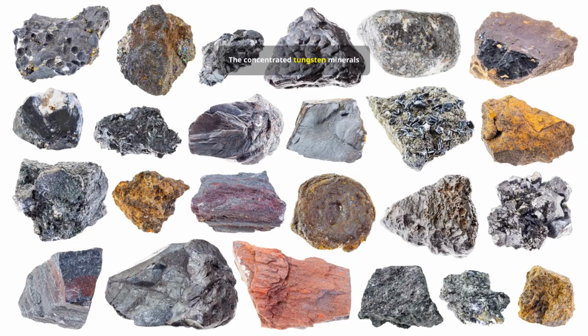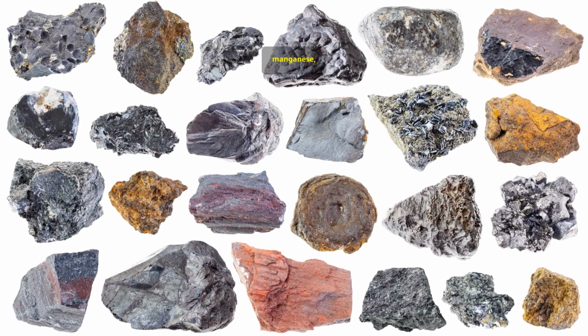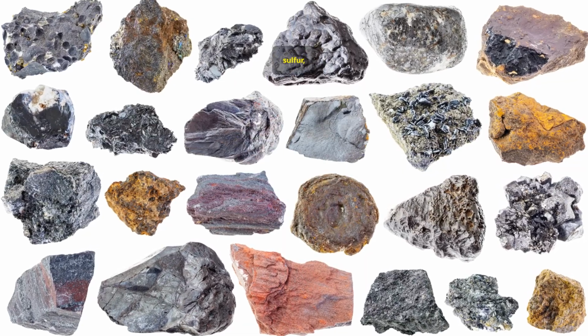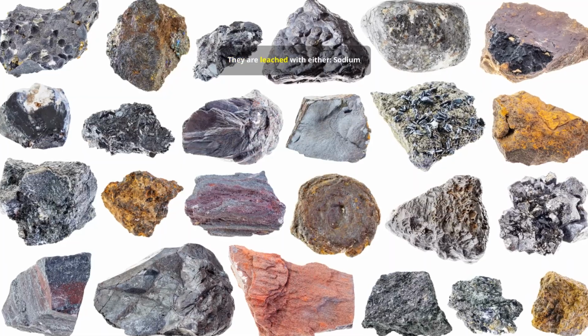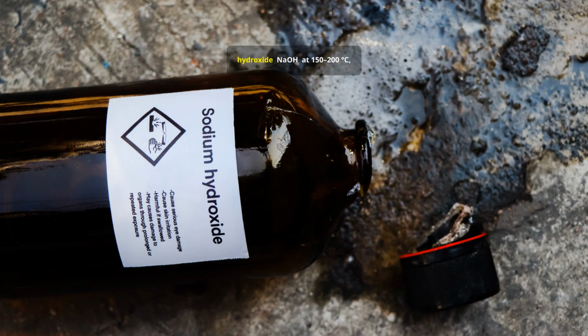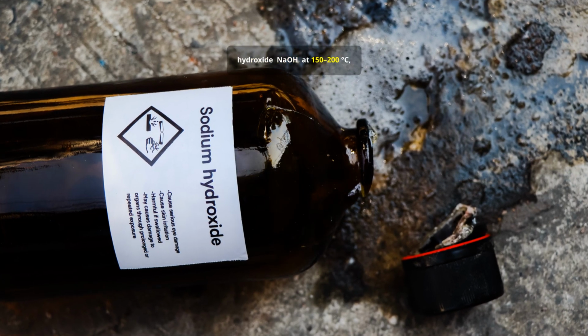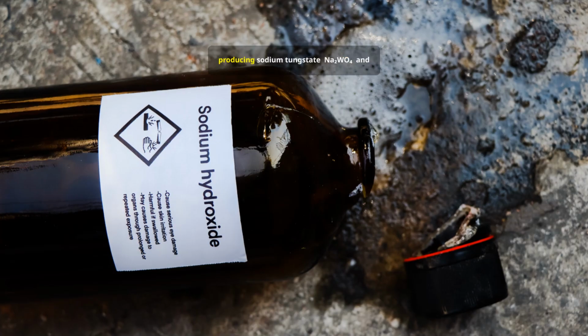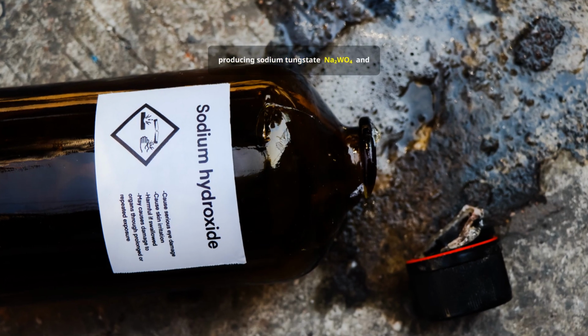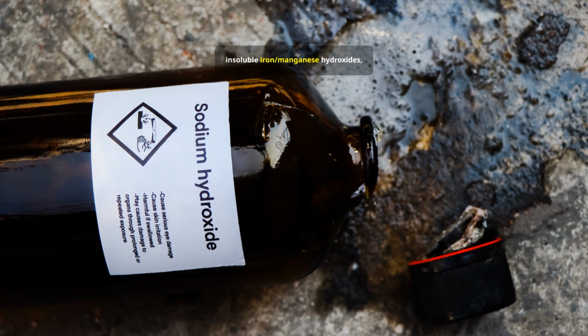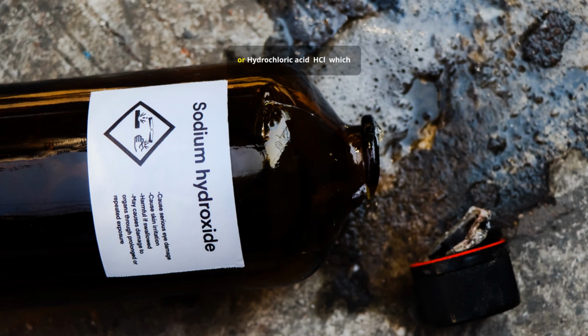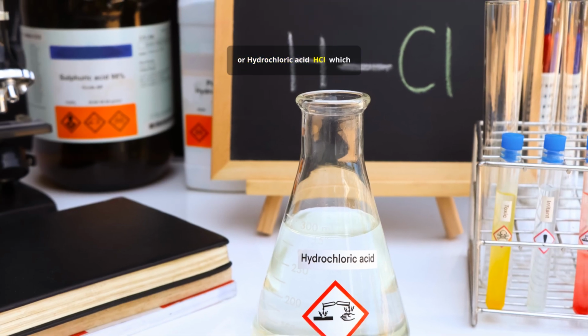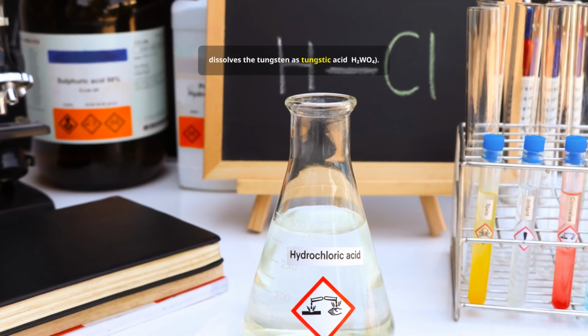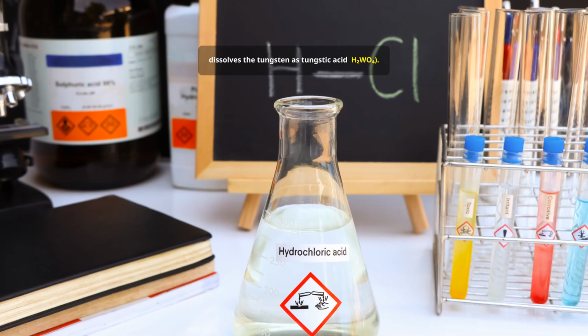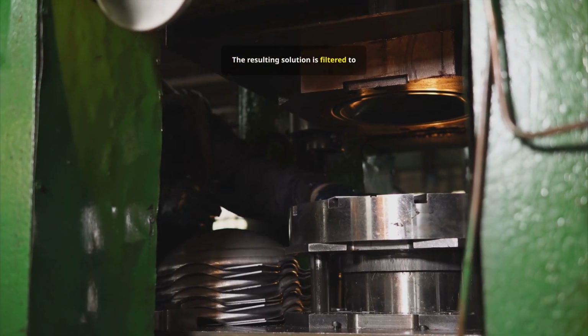The concentrated tungsten minerals still contain iron, manganese, calcium, sulfur, and oxygen. They are leached with either sodium hydroxide, NaOH, at 150-200 degrees, producing sodium tungstate, Na₂WO₄, and insoluble iron manganese hydroxides, or hydrochloric acid, HCl, which dissolves the tungsten as tungstic acid, H₂WO₄. The resulting solution is filtered to remove solid residues.